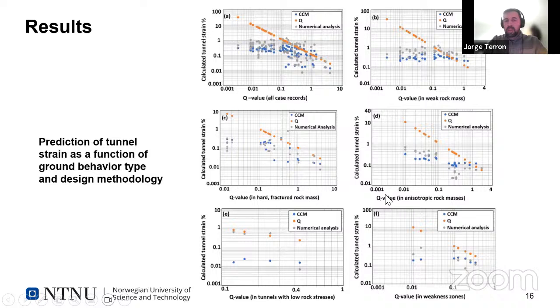If we move to D, which is the anisotropic rock masses, that means rock masses with a preferential joint direction, like, for example, bedding or lamination, then there is almost no agreement. Some agreement can be observed perhaps from Q value 1 and above, but in fact, I don't think the Q system would be very good to prognose tunnel strain or tunnel deformation in laminated rock masses. We did the same for tunnels with low rock stresses and in weakness zones. But for those last two cases, we had fewer case records, so the representativity here is less for cases E and F.